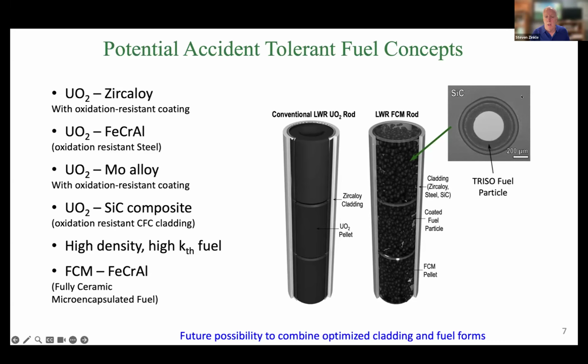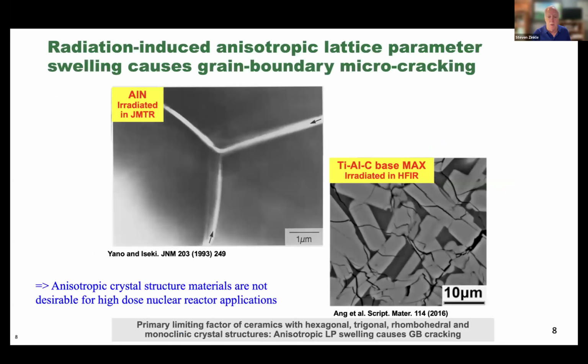And so in traditional TRISO fuel systems, the high temperature gas reactors, the outer layer surrounding the fuel kernels or pellets is a graphite composite material. Potentially, you could have better behavior by replacing the graphite with silicon carbide, and that would lead to a very high performance type of system. But in general, this allows us to mix and match different optimized fuel cladding systems and different optimized fuel forms in the future.